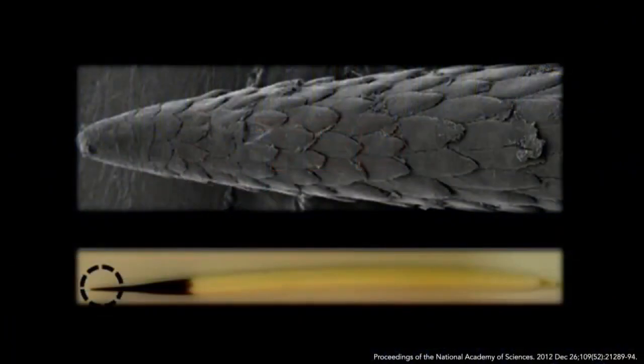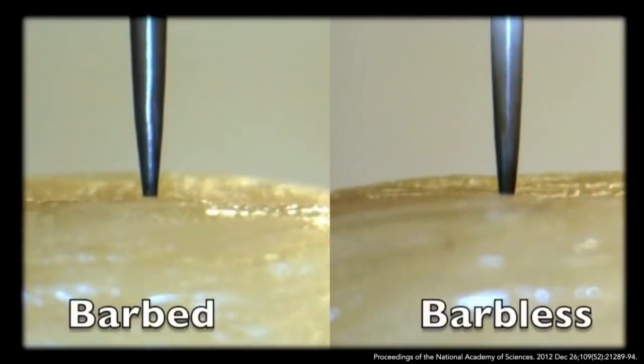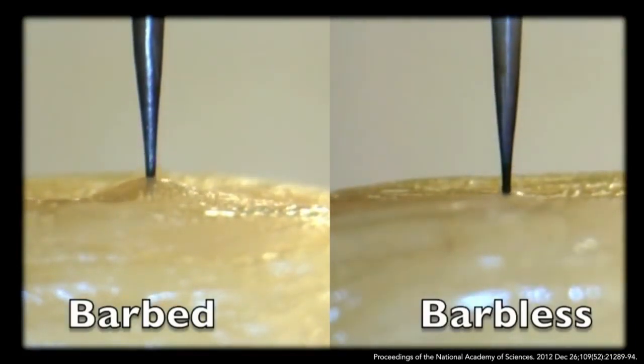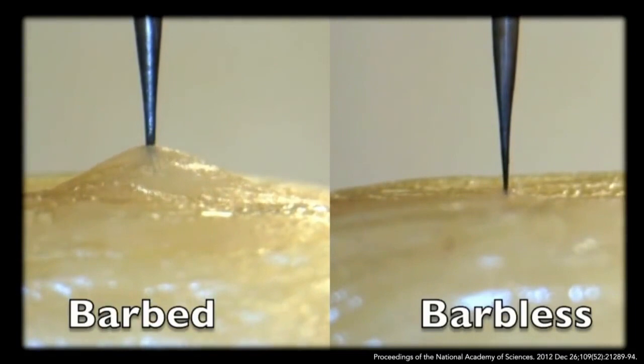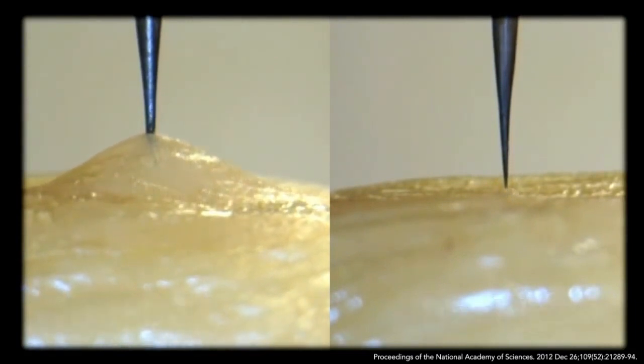These quills have tiny microscopic barbs that decorate the tips that have incredible interaction with tissue. And it's amazing because these barbs are so small. They're the size of a human hair. Look how much pull-out force is required to remove these quills from tissue. We see barbed quills on the left, and on the right, barbless quills. We've just gently sanded those barbs away. Look at that. Pull-out force is important to seal wounds and keep them shut.